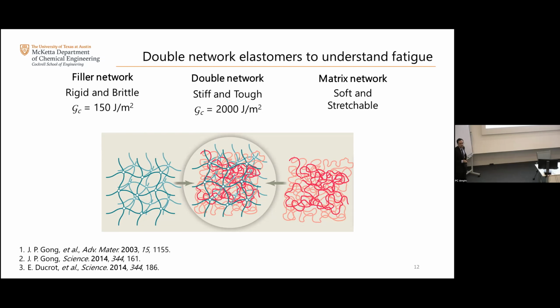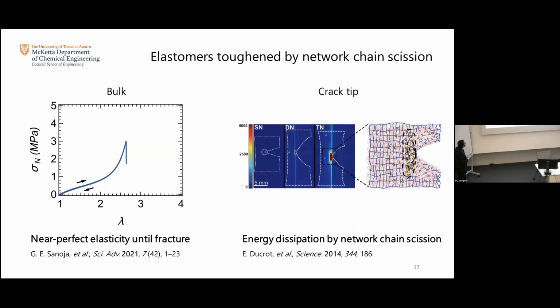And the reason why it's kind of interesting is the following, because you can actually have near perfect elasticity all the way to fracture. So what I'm showing here is effectively many, many cycles that have been applied to a system of loading and unloading. And what you can see is that the system superimposes all the way to the fracture point. You don't have any viscoelastic dissipation. The system is pretty much perfectly elastic all the way to the fracture point while being tough. And that's not very common. In general, systems that are tough are viscoelastic. So this is a system that is tough, but is elastic.